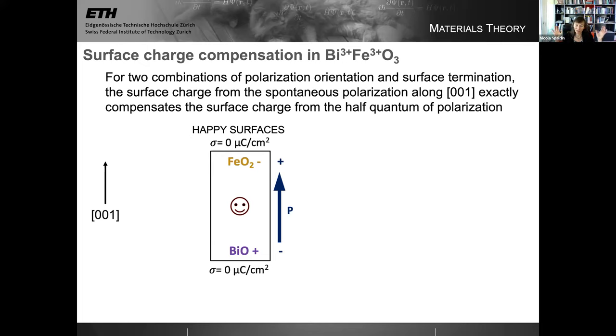There's no diverging electrostatic potential. I can make a very, very thin film of bismuth ferrite, provided I choose this combination of surfaces and this orientation of polarization, and it's electrostatically stable. So this is completely remarkable. I think it's very, very difficult to make a thin film of a ferroelectric and not have it want to explode. And in bismuth ferrite, it happens spontaneously because of this unusual cancellation.